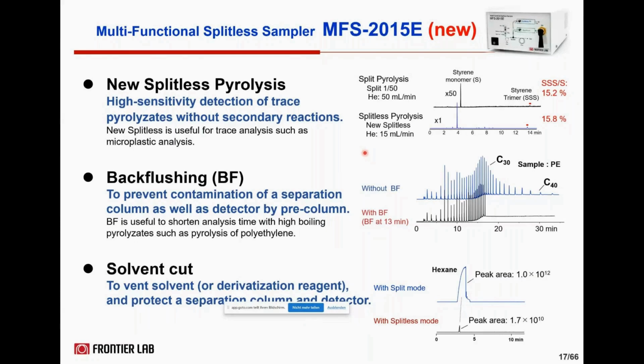The problem is, if you try to use the normal splitless mode using the SSL injector settings, the flow rate would go down to just 1 to 2 milliliters per minute, and compounds would stay a long time in the hot zone, undergoing secondary fragmentations. In the case of polystyrene, the trimer, the pyrolysis breakdown product, would almost disappear. However, the trimer is used for the quantification of polystyrene, for example, according to the new method for microplastics in water. As you can see here, the SSS trimer has almost the same peak abundance ratio in normal split and in the new splitless mode using the MFS.